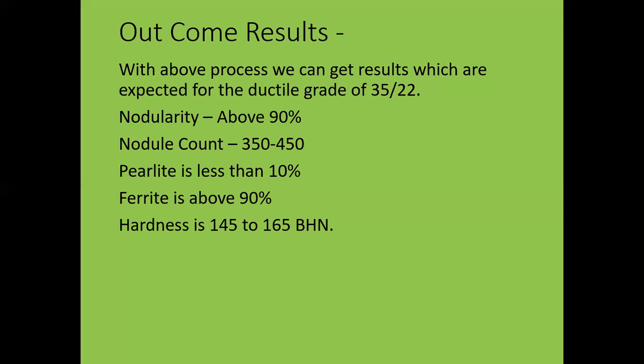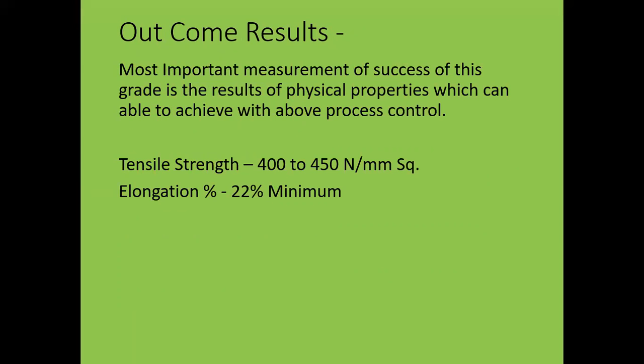Nodularity above 90%, nodule count around 350 to 450, pearlite less than 10%, ferrite about 90%, and hardness will be in the range of 145 to 165 BHN. The most important measurement of the success of this grade is the result of physical properties which can be achieved with the above process control. The tensile strength is expected around 400 to 450 Newton per mm square, whereas elongation expected is 22% minimum.